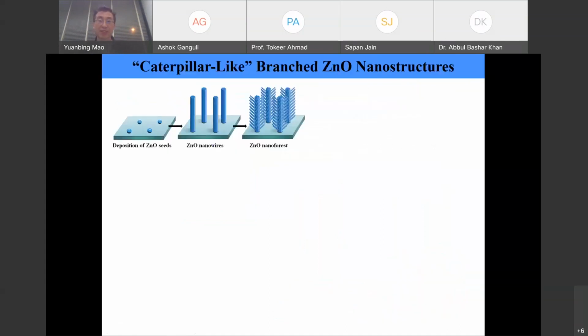So that's good, right? But that's not the end of the story. As I mentioned a little bit earlier, when we apply the zinc oxide nanoparticle seeds, especially the second time, it depends on how we do the coating, right? If the concentration of the zinc oxide seeds is too high, then we will end up with a lot of zinc oxide nanoparticles at the bottom of the nanowire arrays, which is not good. So we've been thinking about how to overcome this issue, because the images I showed you are mostly top views.